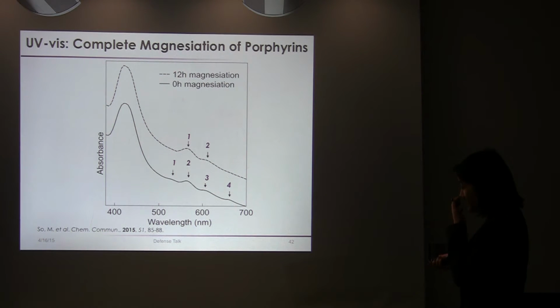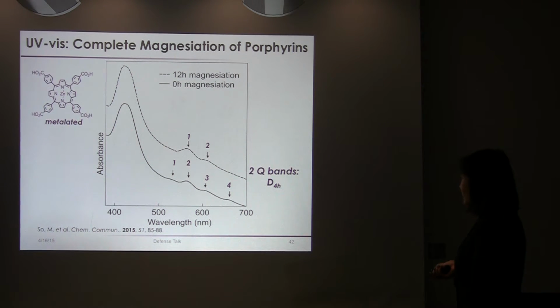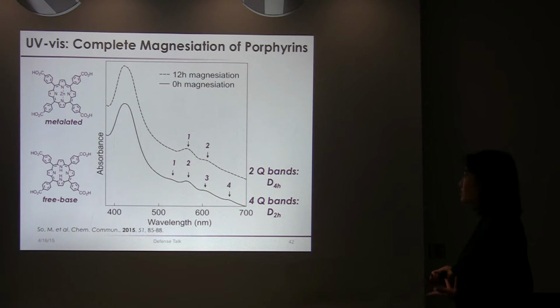And what this showed me was that the pattern of the Q bands came out to 2, which corresponded with a D4h symmetry, and that told me that there was indeed some sort of metallated porphyrin in the LBL film. And that was a great change after 12 hours of magnesiation. Whereas without any magnesiation occurring, I only saw 4 Q bands, which again corresponds to a D2h symmetry for a free-base porphyrin. But this only tells us that there's metallation in the MOF film, but doesn't tell us the identity of the actual metal components.